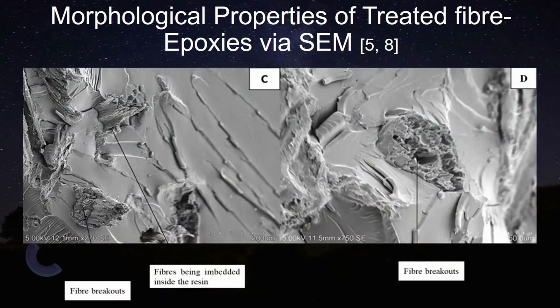And on the other hand, when we did the treated fiber, we got a completely different scenario. We saw that the fiber was embedded inside the resin properly, and that's why instead of fiber pull out, we observed that the fiber broke, and because of that, that whole property will influence its thermal and mechanical properties, and this scenario shows that there is a better fiber matrix adhesion property or better interfacial bonding.